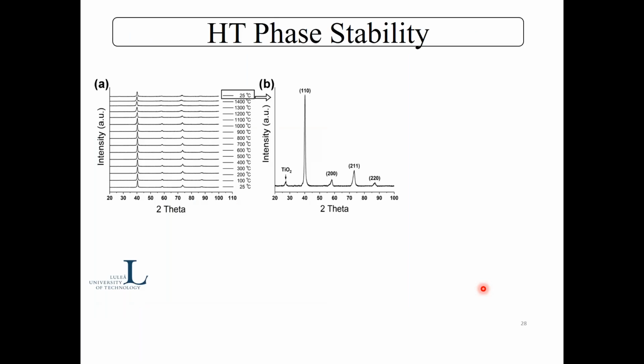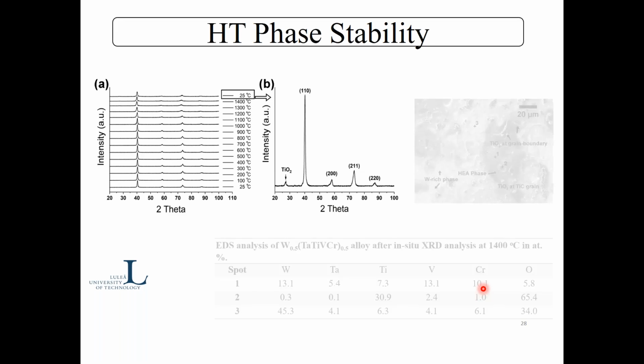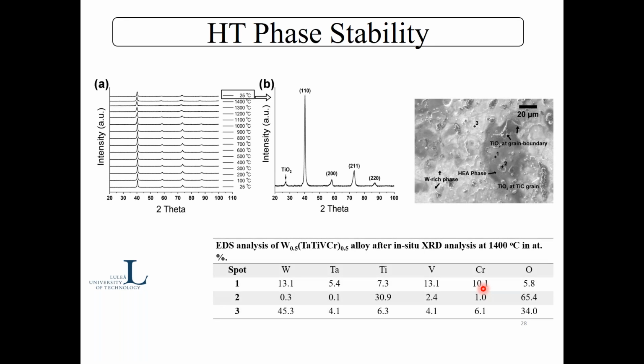And then we checked the high temperature stability by doing heat treatment, heating and cooling down up to 1400. And then we did XRD, and we found that the structure that we form in this high entropy alloy is very stable, and no secondary phase or precipitates appear during the heat treatment up to 1400 degrees centigrade. So the same BCC structure up to 1400, no precipitation and very high mechanical properties. There is no chemical composition change, just a little bit of oxides form.